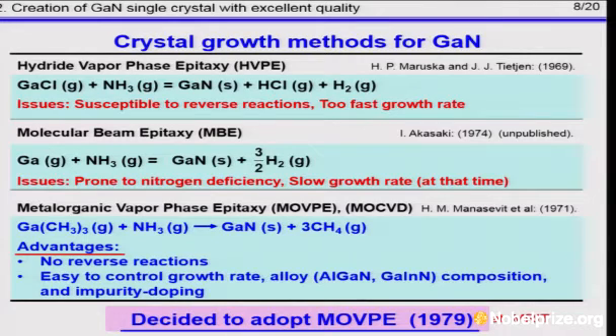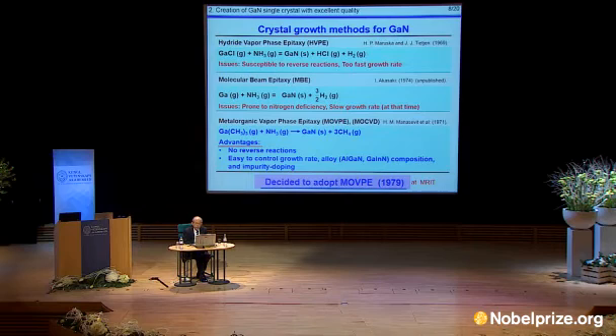and growth rate and the alloy, I mean that alloy is aluminum gallium nitride and gallium indium nitride alloy composition, and also impurity doping could be readily controlled by varying the flow rate of the source gases. Thus, I decided to adopt MOVPE as the optimal growth method for gallium nitride and related alloy in 1979 at MRIT. Today, gallium nitride and related alloy are mostly being grown on sapphire by MOVPE by this method.